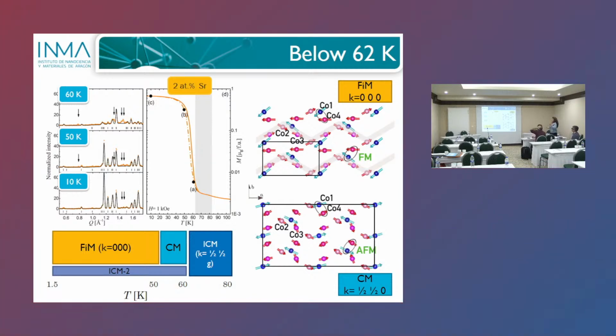This propagation vector is now 1/2, 1/2, 0. So you lose this modulation along the z-axis. The difference between both models is quite difficult to see because they are complex structures. But the main difference is that the ferromagnetic coupling that we observed at low temperatures between these two cobalts now turns antiferromagnetic. So all in all, this structure does not have any net magnetic component, but you need to remember that the neutron diffraction experiments are done at zero field. You don't have any applied field. As soon as you apply some magnetic field, this can change completely. So this is something to have in mind.